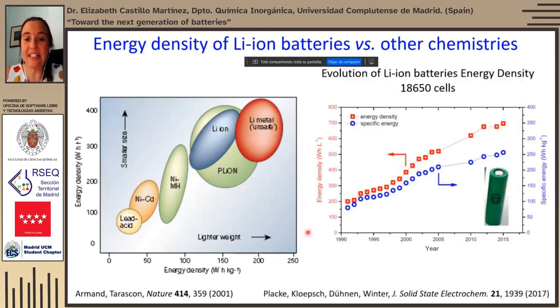If we see how the energy density of commercial cylindrical cells, 18 millimeters in diameter and 65 millimeters in height, has evolved during their 30 years of commercialization, we can see that both gravimetric and volumetric energy density have increased maybe by threefold. And this increase in battery performance is due to both changes in the chemistry of the batteries as well as changes in the engineering aspect.